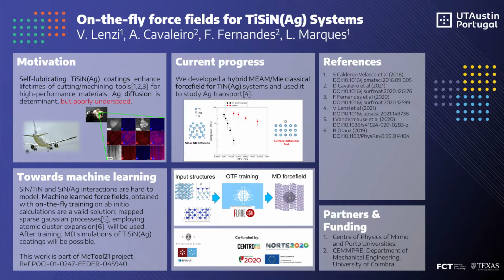Those coatings are formed by many grains, which generates a complex nanostructure, where many grain boundaries and void intergranular spaces are present. The silver transport rate is fundamental in defining the final coating's performance, because silver must diffuse in a controlled way, not too fast to avoid its premature loss, nor too slow or the lubricating effect won't be present.